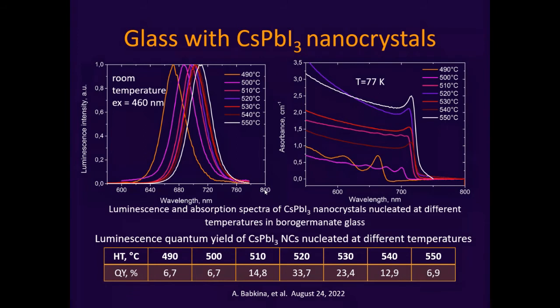The glasses that we have obtained with nanocrystals have a quantum yield that is really good enough. If we are talking about iodide nanocrystals, the maximum quantum yield that we have obtained is 33%. What about literature and other scientific groups? Other scientific groups have not had the opportunity to obtain these nanocrystals inside of the glass matrix with such quantum yield. The maximum quantum yield of other groups in the world was 4%. So we obtained 33, and I think this is a success.